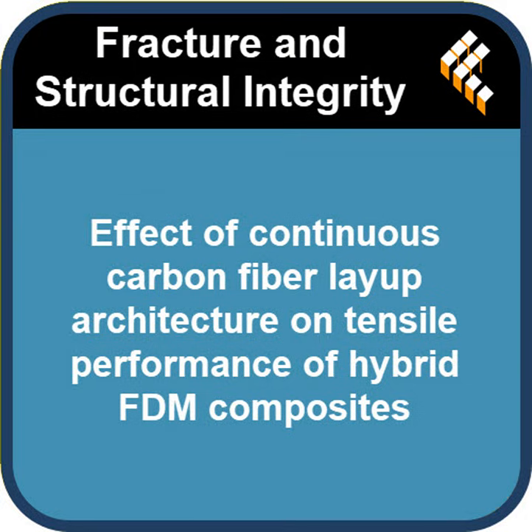How did that specific sandwich perform compared to just mixing up the angles randomly? It drastically outperformed the others. When they tested a layup of 30, negative 30, and 30, which skips that 0-degree spine entirely, it lost 64% of its overall strength. Wow, 64%. So you absolutely need that central load path.